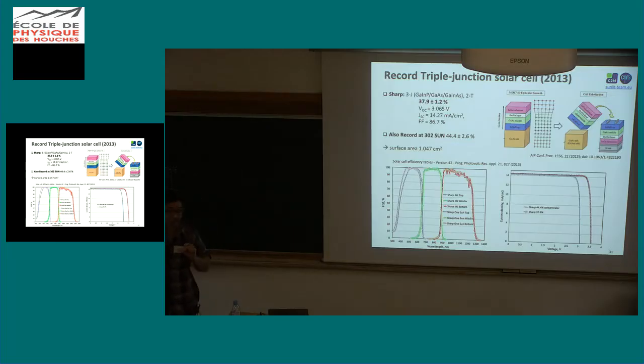So the record triple-junction solar cell is owned by Sharp since 2013, for quite some time now, almost 38%, and it's also the record under illumination at 300 suns, and the surface area is relatively small. So the problem with III-V, as I mentioned before, is the cost. And indeed, to launch a satellite in space is really expensive and it has to stay there for quite some time. So we are ready to pay some money if you want to have a big panel or solar cell in space, but it's not the case on Earth.